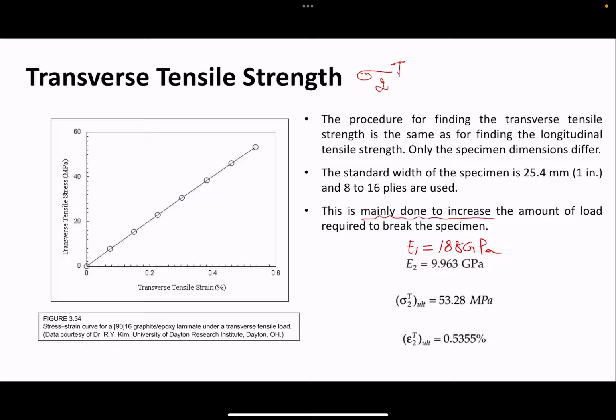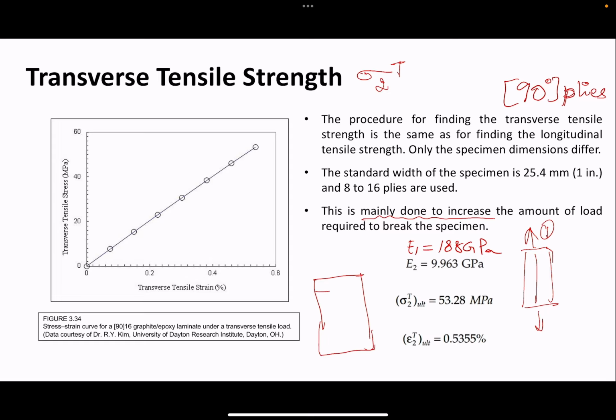And then instead of using 0 degree, you use 90 degrees, I believe, right? So instead of using 0 degree plies, now you're using 90 degree plies, which means instead of doing your lamina this way, this was the one direction, right? Now you're doing the same length, for example, but your fibers are this way and you're pulling at it. And then from there you do the same process, draw the stress strain diagram, and now you can see the values that you get.